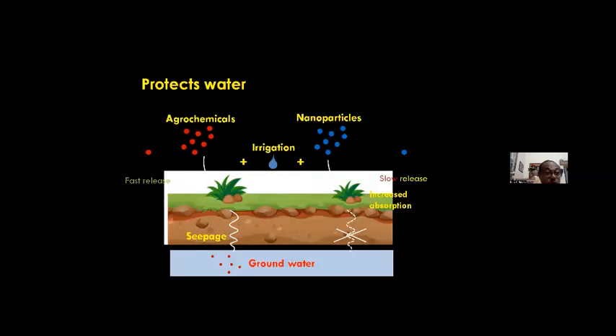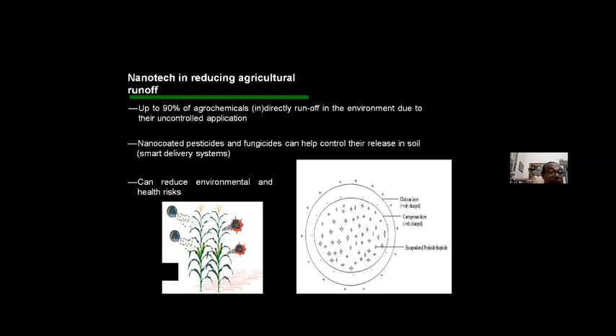It can protect water also. You see, when we are using agrochemicals, there is fast release. So plant retention capacity becomes less, and a lot of seepage is there, and groundwater is polluted. But if we use nanoparticles as agrochemicals or nanoparticle-coated agrochemicals, then there is slow release and absorption is increased. So we found no groundwater pollution is noticed. Again, up to 90% of the agrochemicals directly run off into the environment due to their uncontrolled application. But if we use nano-coated pesticide or fungicide, that helps to control their release in soil and can reduce environmental and health risks.